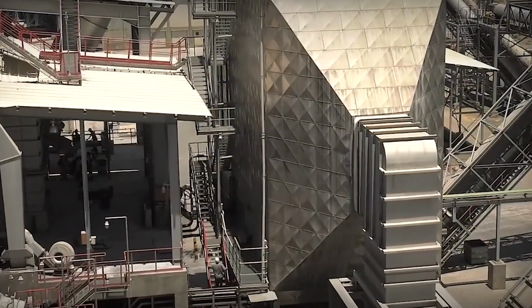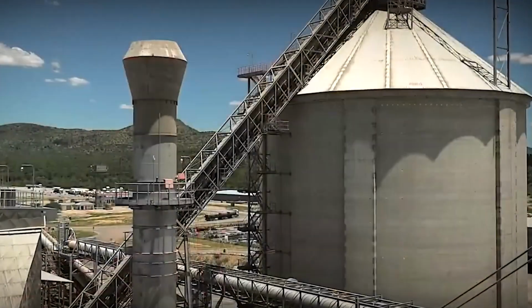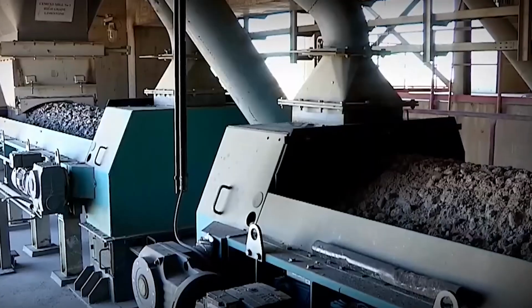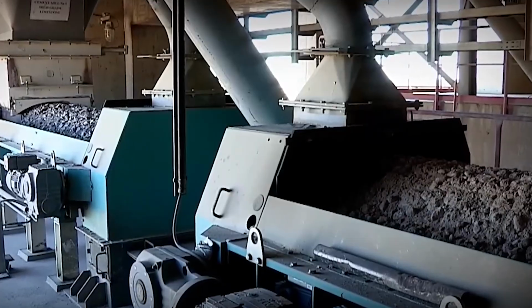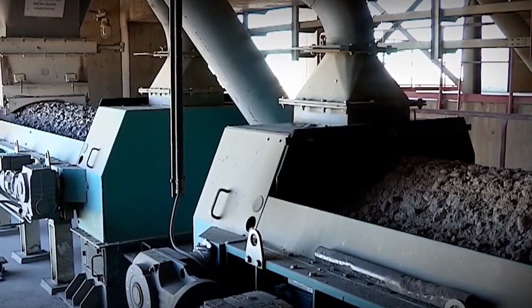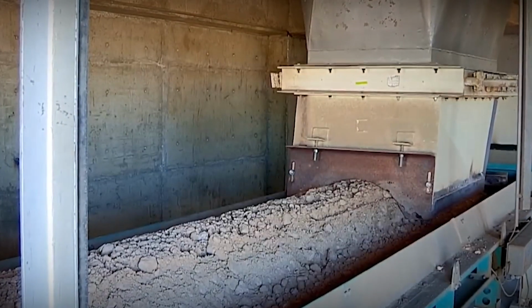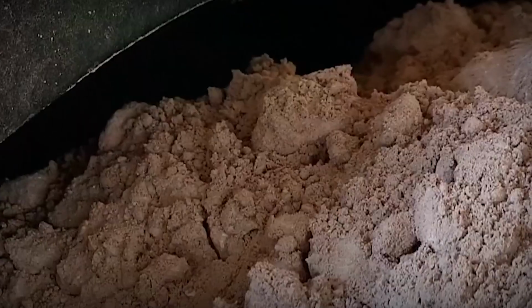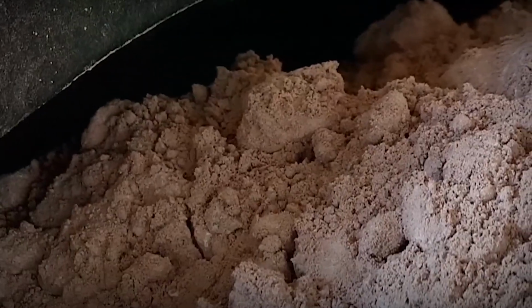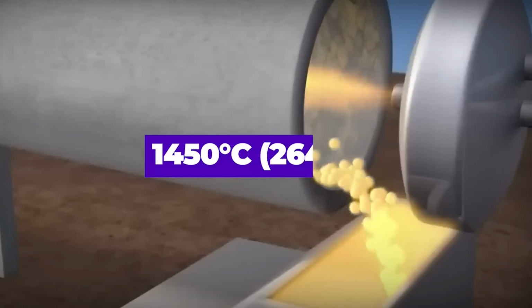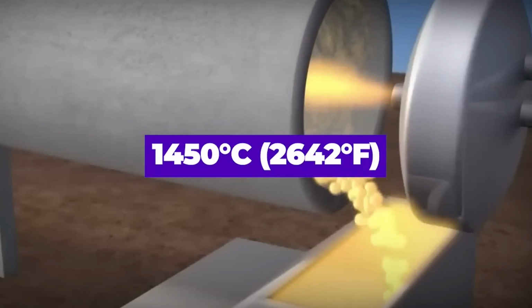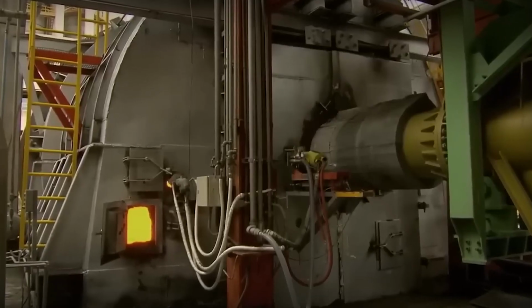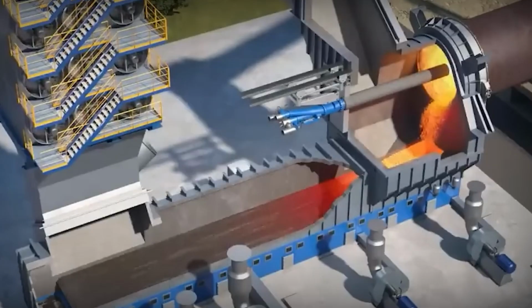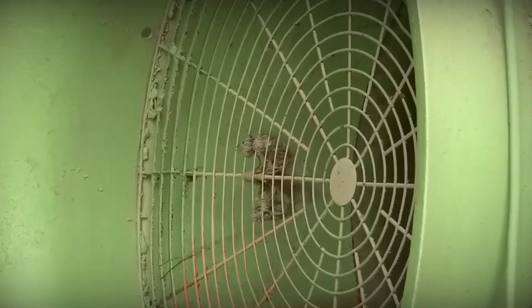As the temperature increases further, the materials begin to react and partially melt. This leads to the formation of new compounds such as tricalcium silicate and dicalcium silicate, which are responsible for cement's strength. At the hottest point in the kiln, the material forms small, dark gray nodules known as clinker. These clinker nodules are the core product of the cement-making process. They look like small pebbles, but contain all the essential compounds needed to produce cement.